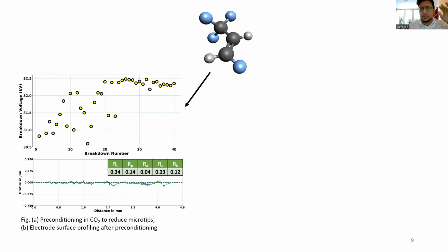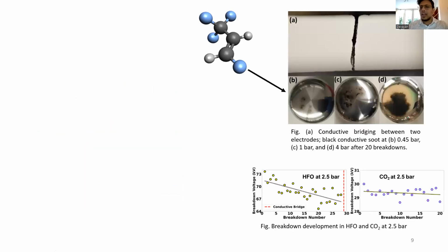So HFO seems to be a pretty good gas, right? Low GWP, non-toxic, low normal boiling point, but it's a really ugly gas. Why? Let's have a look at pictures B, C, and D. B is for 0.45 bar, which is really low. Then we did 1 bar, 4 bar, and also other pressures in the middle, but these are the important ones. At low pressure, you have the low energy breakdown, so for low energy, you still have a small amount of carbonization. But as the energy increases, you have ugly sooting on the electrodes.